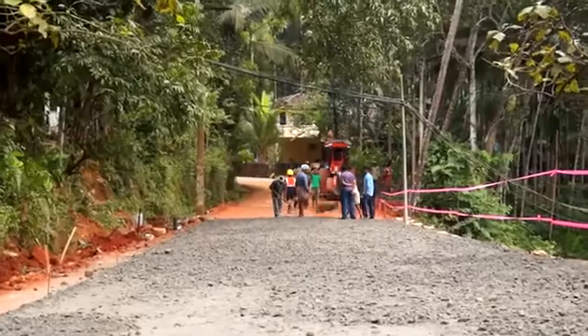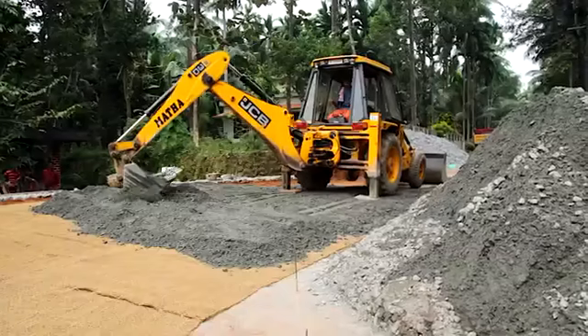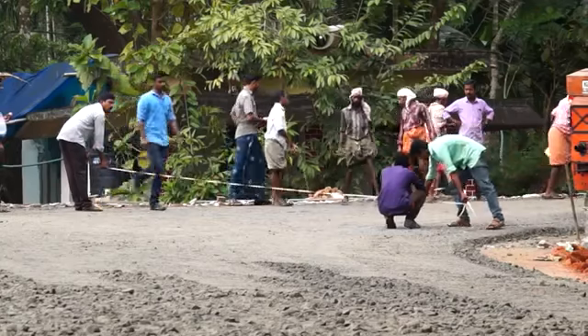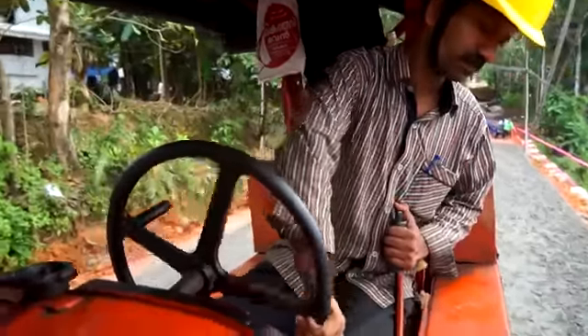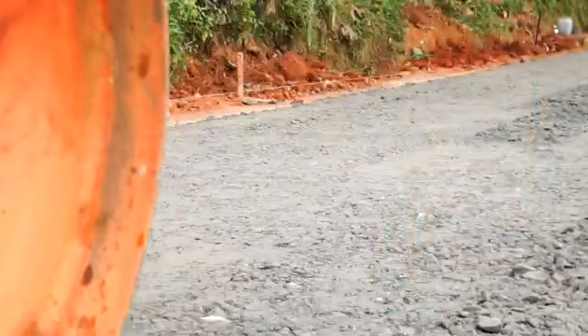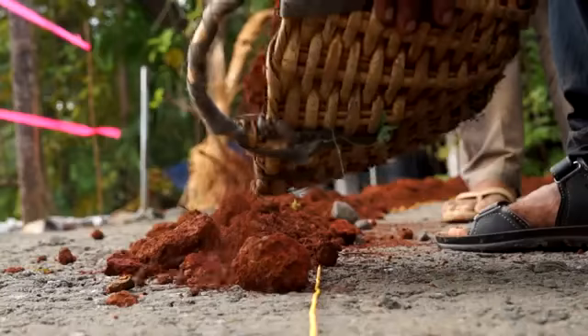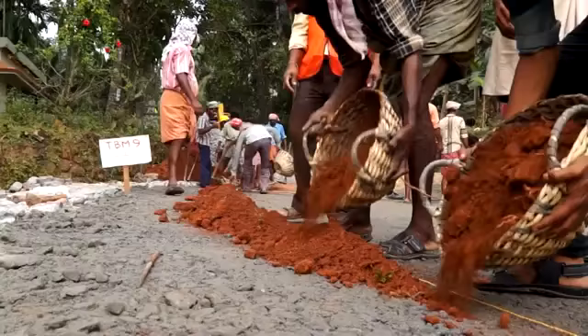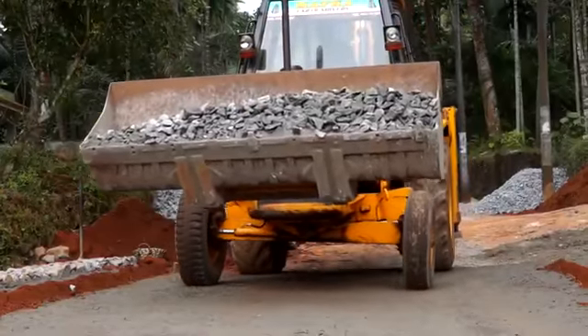The dumped material is then evenly spread either manually or mechanically by using the JCB to the designed thickness. Then the profiles are corrected manually for the required camber and super elevation. A roller is then used to roll the material to 100% compaction. After finishing the GSB layer, the shoulders are maintained with good gravel earth for spreading the grade 2 material as base layer, the width of which is 3.8 meters.